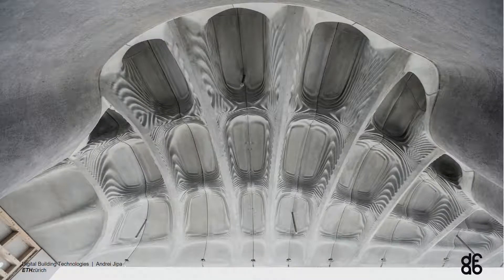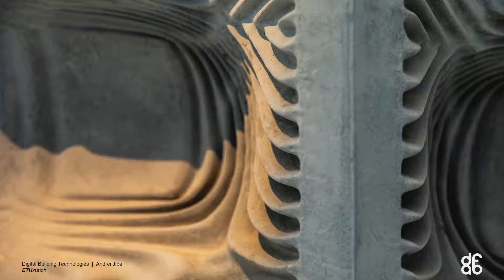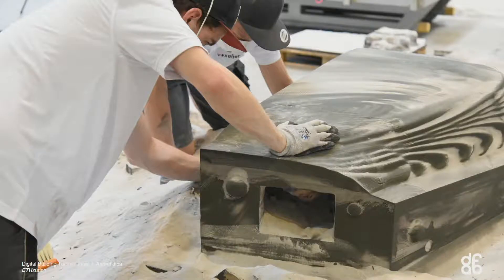This is a smart slab. It was part of a larger effort to combine digital fabrication into a functional building — about 80 square meters. Here we use some computational optimization processes. Because of the geometric freedom we have, we manage to reduce the weight of a standard concrete component by 50 to up to 70%. And as architects, we're always excited about the geometric freedom that 3D printed formworks allow — sharp edges, great details, undercuts, microstructures which are maybe a few millimeters in size — which we cannot achieve with any other fabrication process accessible to concrete.